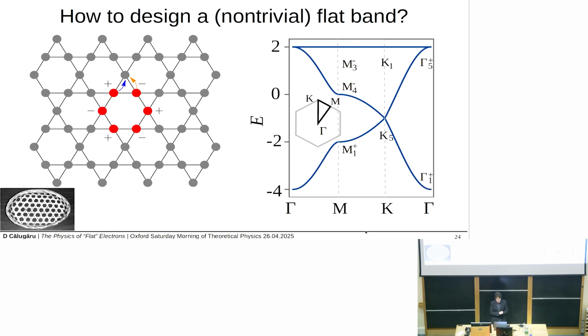This is a linear combination of orbitals with alternating signs around the hexagon. Now here's the key. Because of the lattice geometry, any tunneling outside of this hexagon exactly cancels. The destructive interference is perfect. So this wave function is an exact eigenstate that I can write down for every hexagonal plaquette of this Kagome lattice. So if you go ahead and Fourier transform and do the proper computation, on the right-hand side you find that you get a flat band here at energy equal to 2. I'm working in arbitrary units where t is equal to 1.